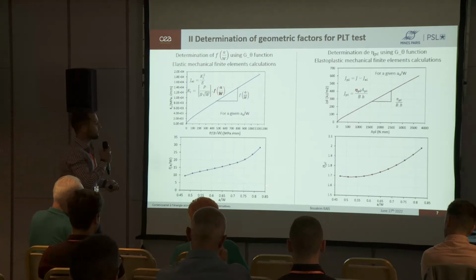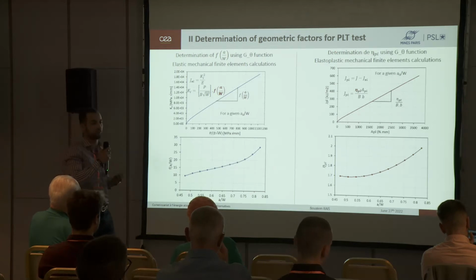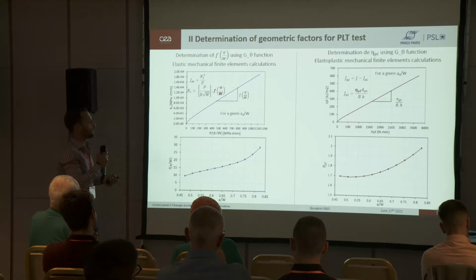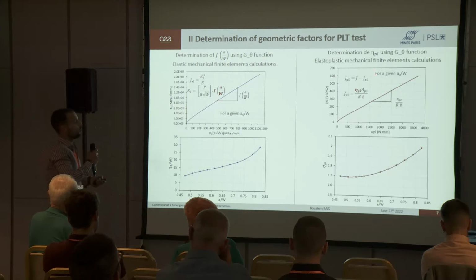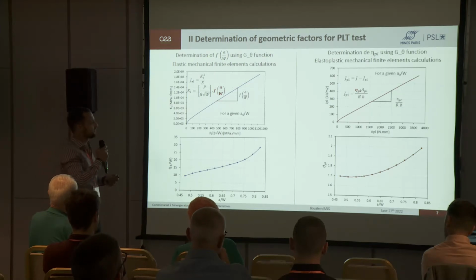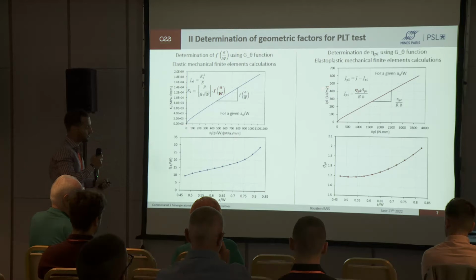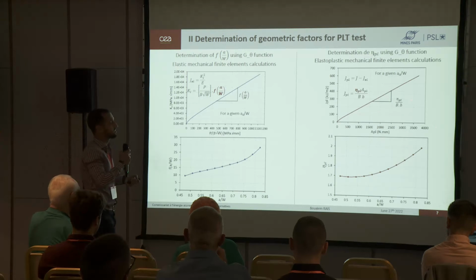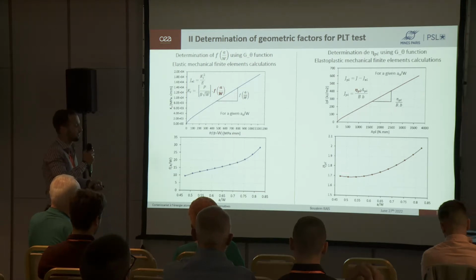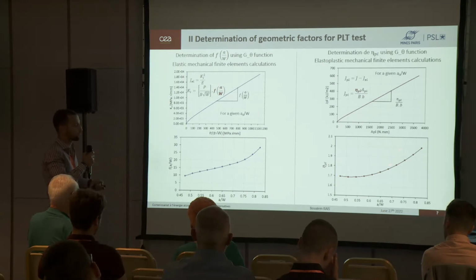Now, the eta factor, or the plastic factor. For this, we perform some elastoplastic mechanical finite element calculations, and determine the J integral, which is a total J integral. But knowing the F function, we deduce the elastic J and determine the plastic J, which is the total J minus the elastic J. So the evolution of this plastic J as a function of the plastic area under the load CMOD curve is linear, and its slope is our eta factor multiplied by a constant that we know. As for F, we repeat the exercise for different normalized crack lengths to have the evolution of this eta factor.